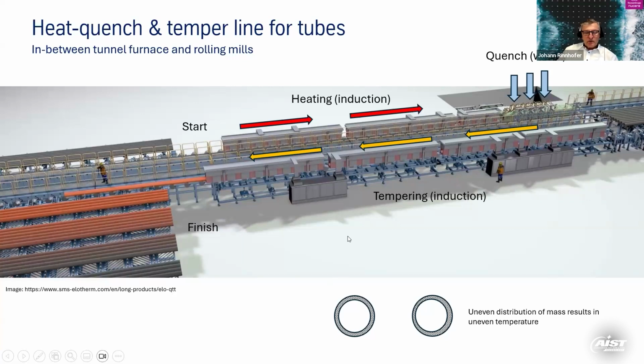come out here on the cooling table, and that's the end. Very, very good concept, very small footprint, but you have to be careful because API standards, they also allow some eccentricity of the tubes. So you might have some material thickness which is different from one side to the other side, and that has an impact on the heating because the temperature will be much higher in the smaller area, in the thinner area, so to say. So you have to be careful when you do that.